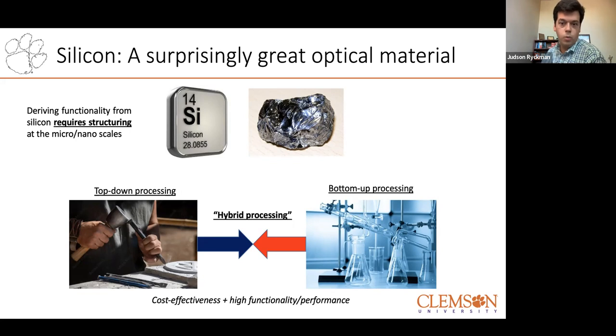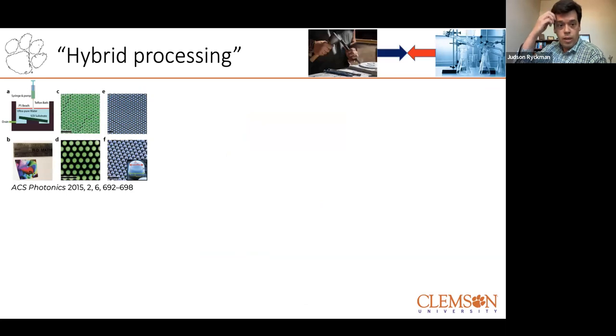And so we're going to look at this with silicon as an example. So one example, this is work not from my group, but this is Jason Valentine's group out of Vanderbilt, where they've taken polystyrene beads, which can self-organize into a close packed arrangement on a surface. So that's kind of your self-organization piece. But then you can do top-down processing and put it into the clean room, do reactive ion etching. And so now you have a nice arrangement of these Mie resonators on the surface with a tunable size, and they give a very strong coloration, tunable spectral properties on the surface.